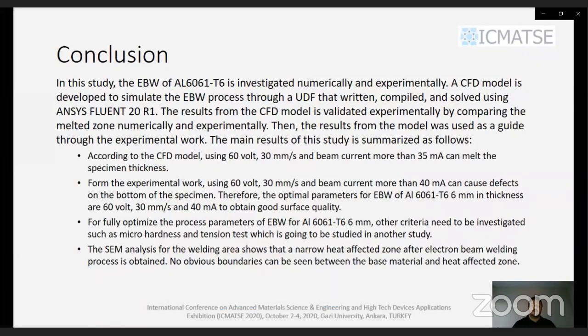According to the CFD model, using 60 volt, 30 mm per second and a beam current of more than 35 mA can melt the specimen thickness. From the experimental work, using 60 volt, 30 mm per second and a beam current of more than 40 mA can cause defects on the bottom of the specimen. Therefore, the optimal parameters of electron beam welding of aluminum 6061 T6 condition, 6 mm in thickness, are 60 volt, 30 mm per second and 40 mA to obtain a good surface quality.